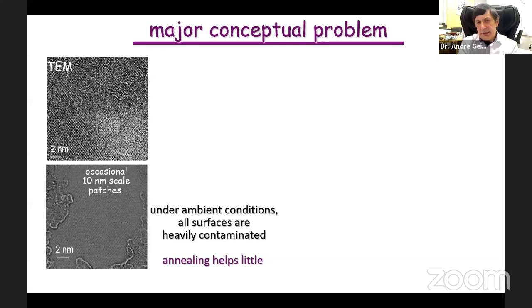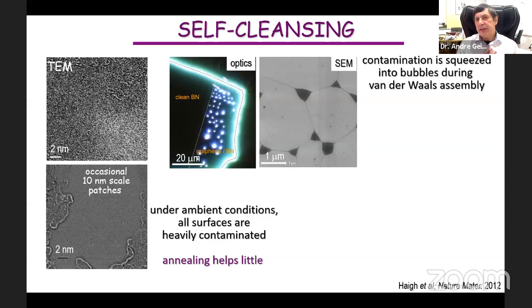So I actually thought that this project, which I gave 5 years ago to a postdoc at that time, Radha Boya, an Indian national who started working with me, wouldn't work as well as it worked out. I thought something interesting would come out, but didn't expect that it would be properly working. Fortunately, it worked better for a very simple reason, because when you put crystals on top of each other, they attract very strongly by van der Waals interaction. Van der Waals interaction is considered very weak, but when you are talking about angstrom distances, it's rather a powerful force, something like it can create pressures of about 1,000 kilobars.